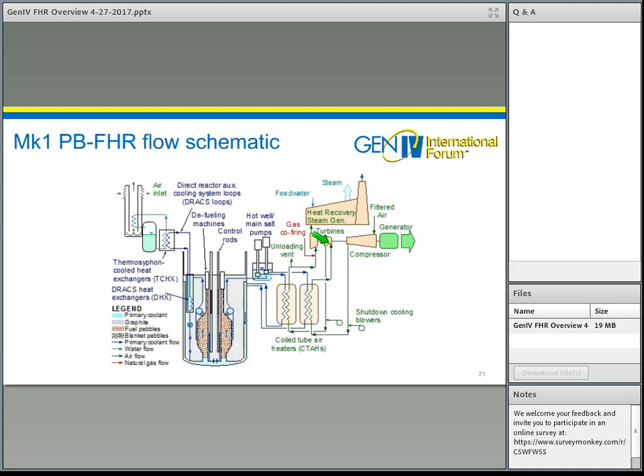It then goes into the turbine and expands back down to about 5 atmospheres, where it's back at about 420 degrees and can be reheated. The reheat stage is what makes it possible to operate in a base load mode with purely nuclear heating. And so at 670 degrees, this air then expands down to atmospheric pressure, and then residual heat is removed in this heat recovery steam generator. Gas co-firing in this location can boost the temperature going into this turbine and therefore boost the power output.